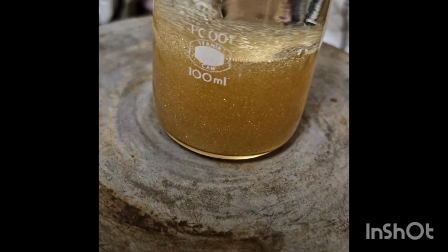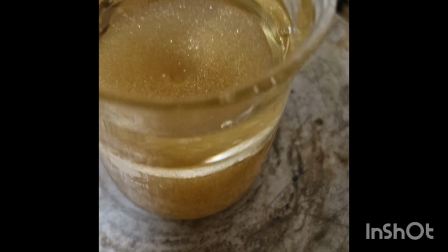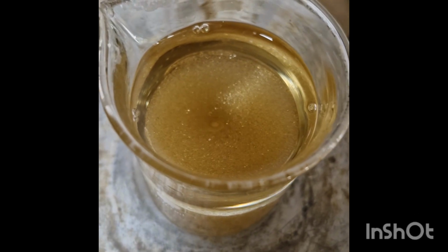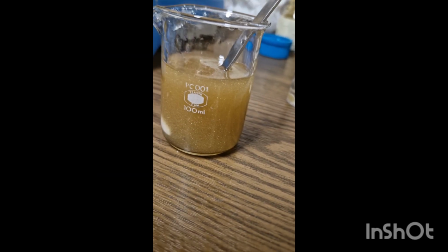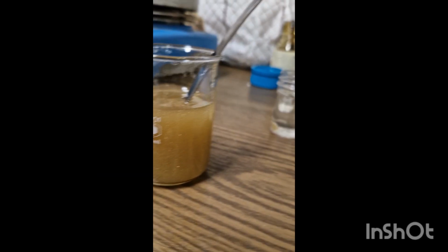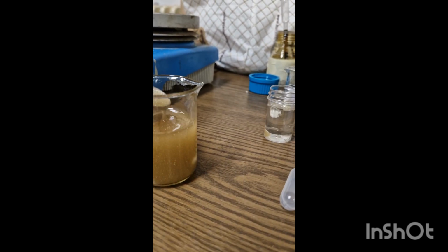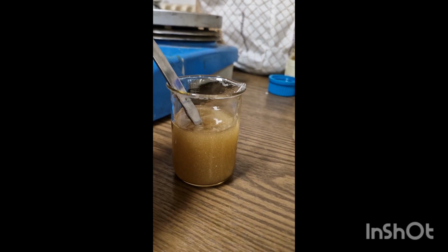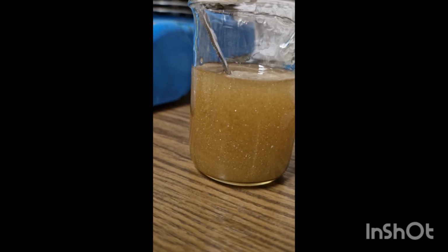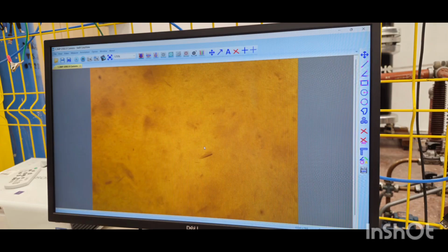So at first you can see in this video that we have 2 distinct liquid phases. This is because graphene oxide is hydrophilic and does not easily disperse in all solvents. To solve this, and disperse the graphene oxides in the oil, we introduce a polymeric surfactant or compatibilizer, which helps stabilize the dispersion into a single-phase mixture. So in the final solution, you can see that it becomes visually shiny and uniform, which indicates a stable composite mixture.